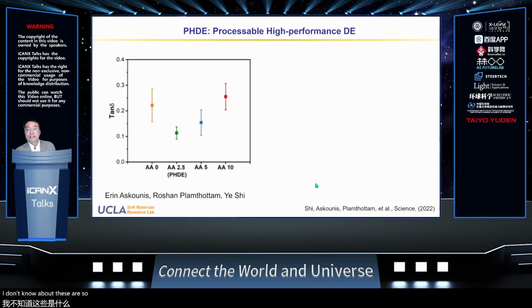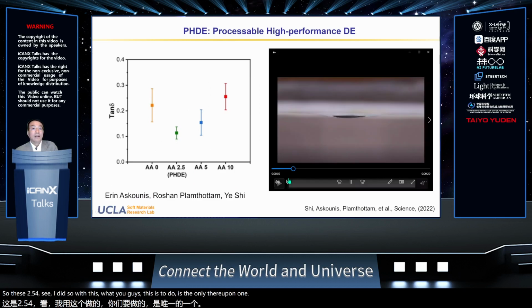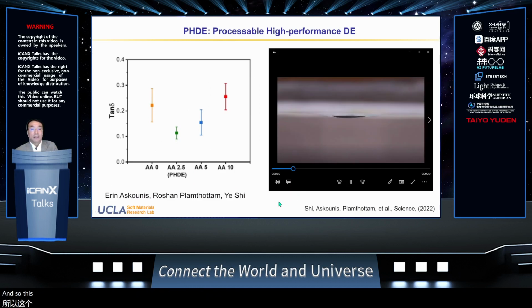So this is the acrylic acid. You will see in this chart here that without the acrylic acid added, it has a tan delta, the mechanical loss, or the viscoelasticity measurement, of about 0.22. With 2.5 parts AA added, the viscoelasticity is reduced to only 0.1.